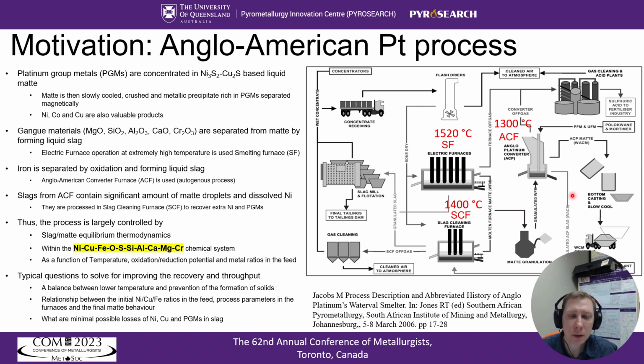Since the matte is sulfur deficient, during the cooling, metallic nickel-rich phases precipitate out, and PGMs preferentially concentrate in those metallic phases. They can be separated magnetically and further processed. So, nickel and copper and a small amount of cobalt are valuable byproducts. The first pyro step is electric furnace, which must operate at very high temperatures due to the presence of magnesium oxide.